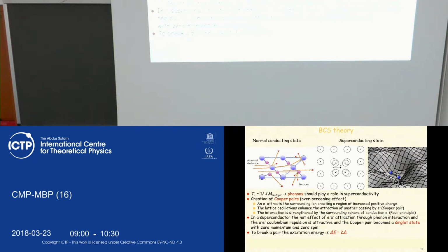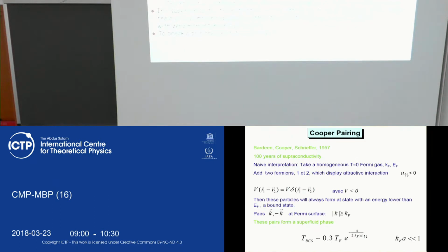And in most known superconductors, the mechanism of pairing of electrons to form Cooper pairs is mediated by phonons. And as we have discussed, in most of the superconductors, the Cooper pair is a singlet. In order to break the Cooper pair, one needs to pump energy of the order of 2 delta, which then destroys this paired state. Let me briefly flash also the ideas of the BCS theory.